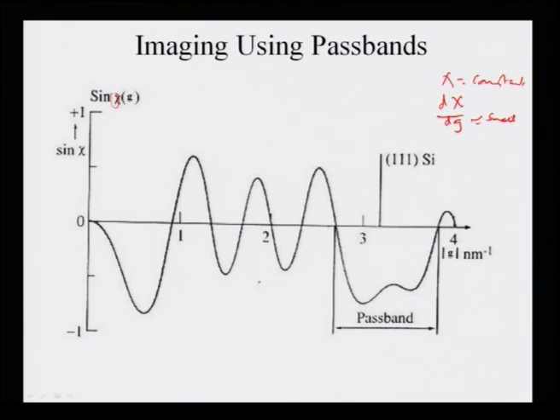As you can see, sin chi is varying from minus 1 to plus 1 as a function of g here. G is the spatial frequency, and there are many pass bands. If I select a pass band which corresponds to the 1-1-1 reflection of silicon, I can clearly see that chi remains almost constant from this part to this part of g, and d chi by dg is also very small. That means it is not 0, but is a very small value.